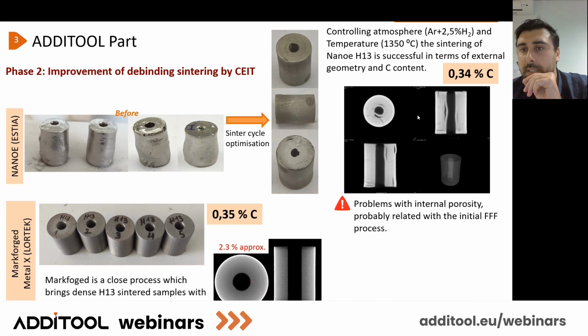We have still some porosities, but this is due to the difference between the manufacturing strategies, because you have a contouring perimeter outside and the infill. And so we have to retake the parameters to oversee exactly the overlap between infill and perimeter, but we have still some internal porosity due to the process.